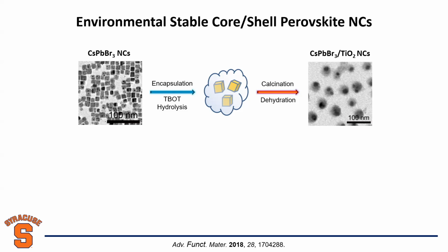We thought, how about we grow oxide on the surface? How can it be oxide, right, in air? So that's what we did. We grew titanium dioxide on the surface of perovskite nanocrystals. But that's a challenge here in chemistry synthesis. We want to make an oxide. Usually you start with metal precursors in water solution under a hydrolytic reaction. We know perovskite has very poor stability in water. How can we do a hydrolytic reaction in water, right?